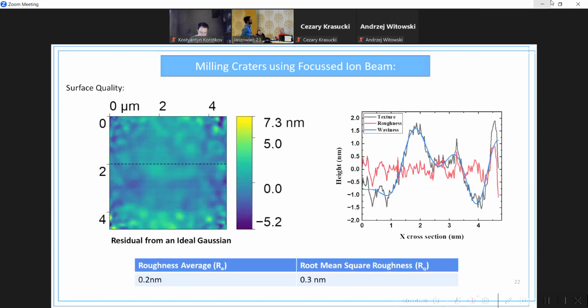You can do it more quantitatively and take a cross section across this image, and you see that this black line is the texture across this cross section. There is a slight waviness in the shape of the crater, although the roughness itself is quite low - almost optical quality. We were quite happy with the results, although there is a slight waviness of a few orders of nanometers.